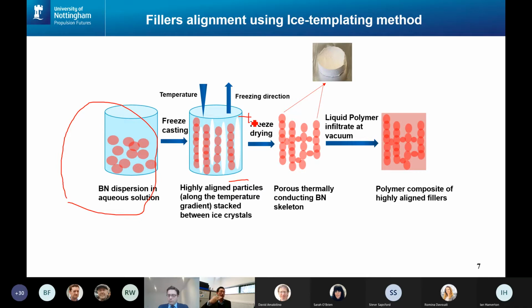Because there is a very high temperature gradient, the ice starts to grow from bottom to top, which sets the direction of ice crystal formation. During this procedure, the particles put inside can actually slightly tailor themselves to fit the ice crystals, and then we finally get the alignment done. So this is how it works.